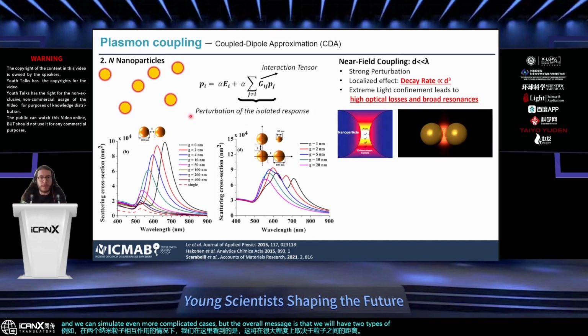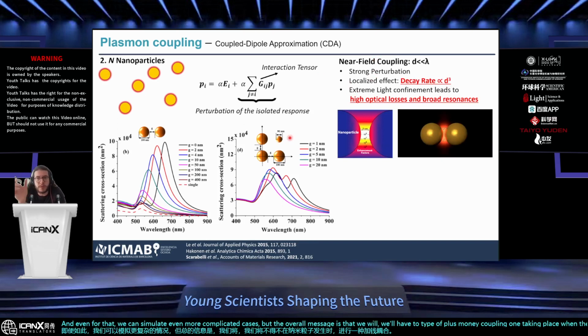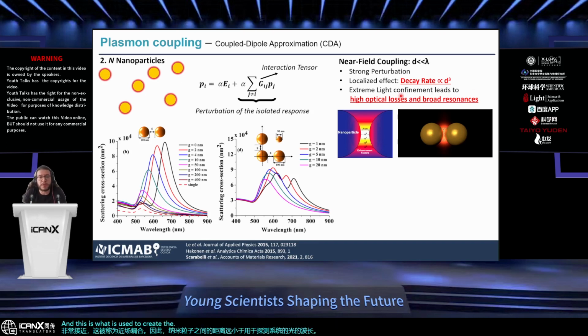We can even simulate more complicated cases, but the overall message is that we'll have two types of plasmonic coupling. One takes place when the nanoparticles are very close, which is called near-field coupling, where the distance between the nanoparticles is much smaller than the wavelength of the light used to probe the system. And this is a very strong perturbation, and this is what is used to create the hotspot. So basically, the plasmon of each nanoparticle will interact with each other and will hybridize, very similarly to what a molecular orbital will do in a molecule. And so we create a very intense area between the nanoparticles where the generated electric field will be very intense.